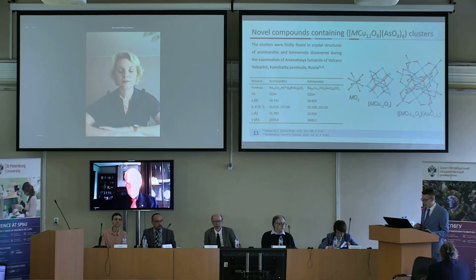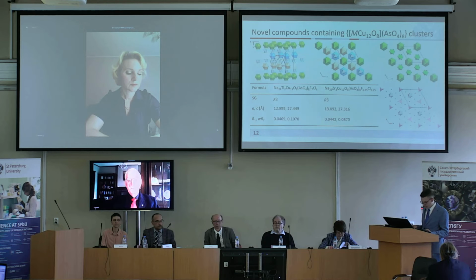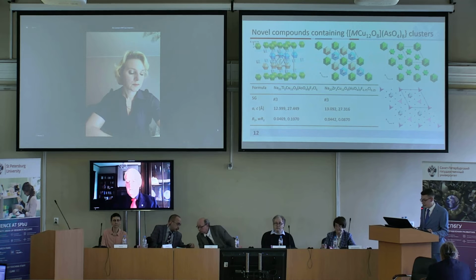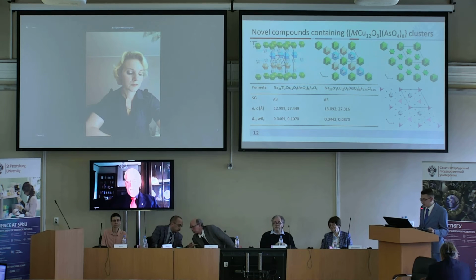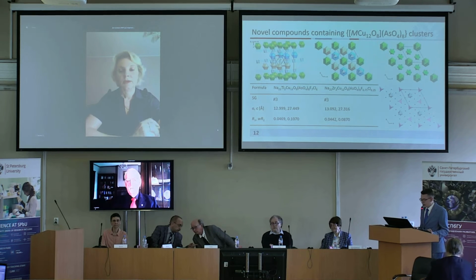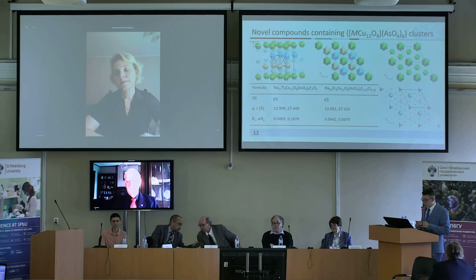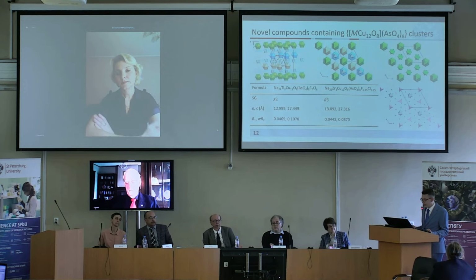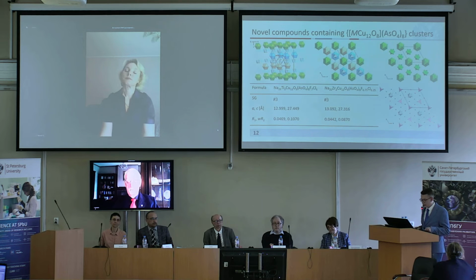We synthesized 5 new compounds containing such clusters. The first 2 compounds were titanium and zirconium containing, with the clusters forming the 3-layer cubic packing. At the same time, the structure contains additional MO6 octahedrons, where M stands for titanium and zirconium, which are located in the octahedral cavities. The sodium atoms retain features of the halide structure.